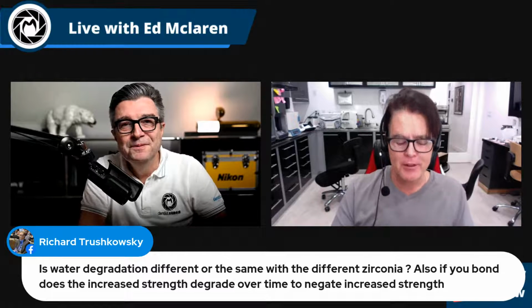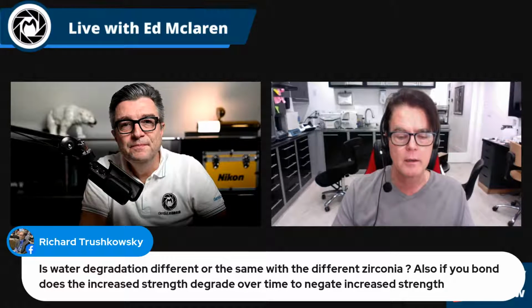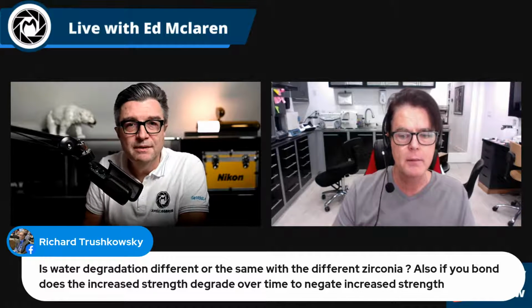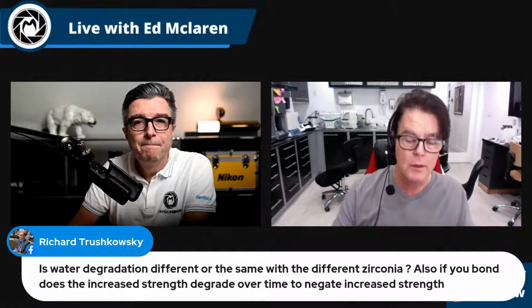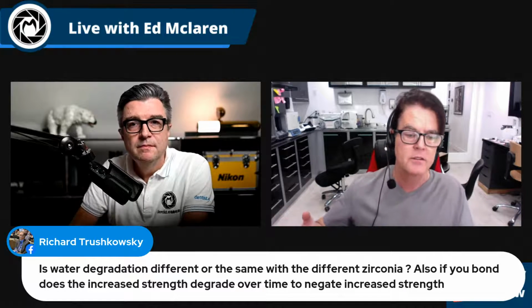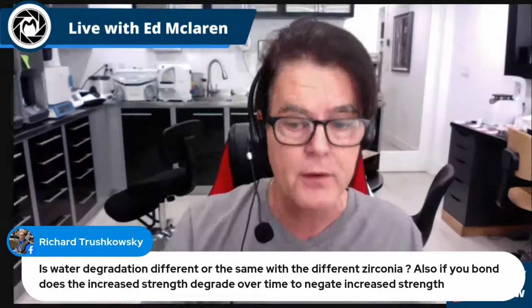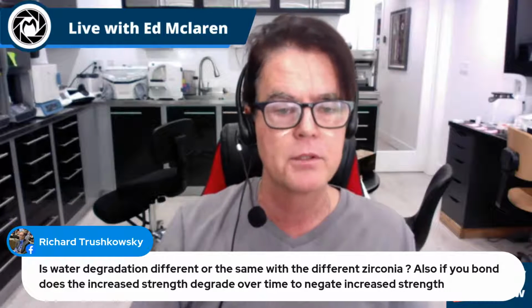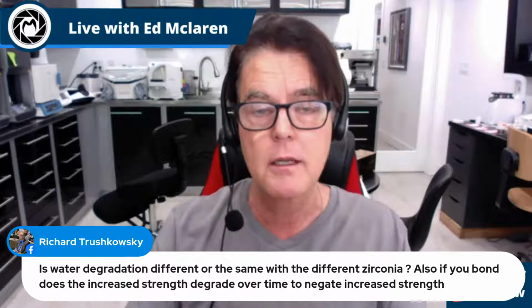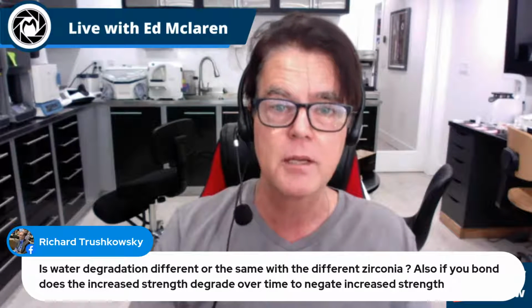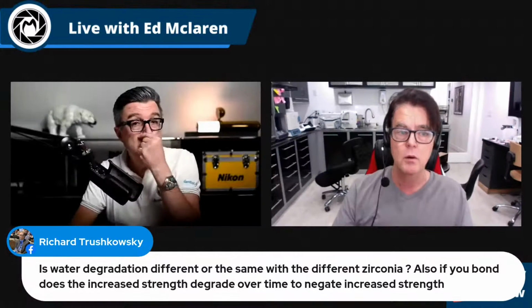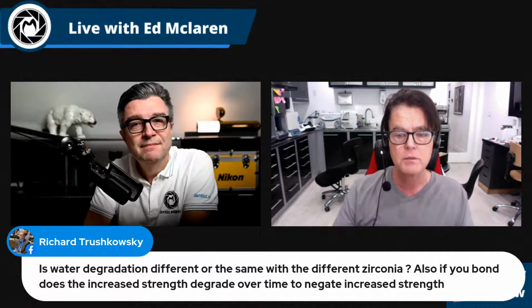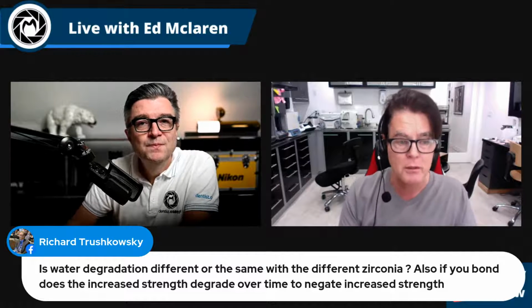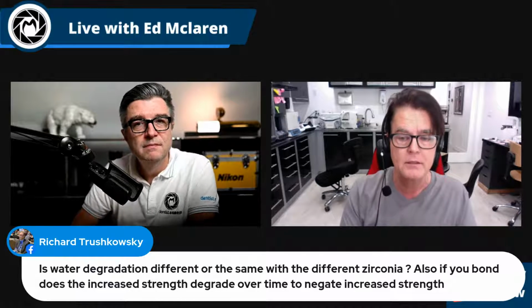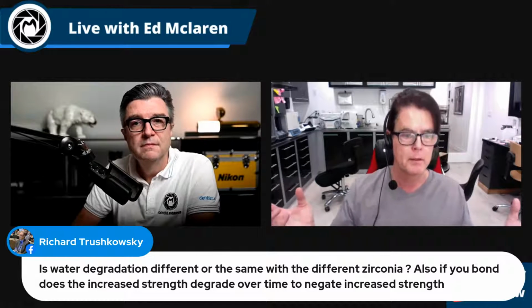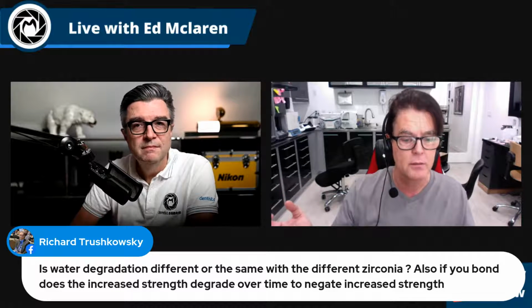Okay, well, the helicopter thing I heard about, but that all came from essentially the hip implants, right? Yeah. Hip implants were done with and without alumina as a dopant, and the ones without alumina in them are definitely more susceptible to low temperature degradation. The monoclinic form on the surface changes. What that does is sometimes create compression that you don't necessarily want, a breakdown of interfaces of grains, which makes the material weak. And so there were actually reports in the medical literature where hip implants done without the alumina material blew up. I mean, they basically disintegrated in people's hips because of the reaction to water.